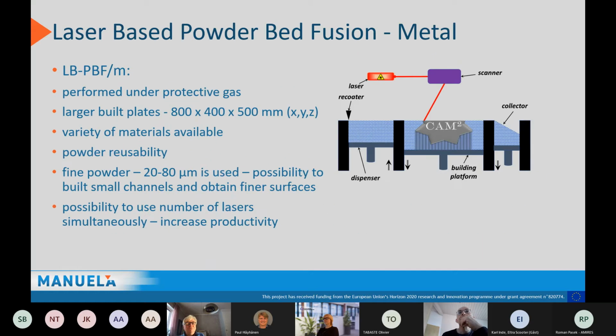Next slide, please. And then we go up to the two technologies. This is a little bit the textbook. If we look at laser-based powder bed fusion, where we use metal, we use a protective gas. We can have quite large build plates, up to 800, 400, 500 millimeter in X, Y, Z. Quite a good range of materials available. We have good capability to reuse the powder, because of course we don't use all the powder in the product we build. So the technology itself must be built so that we have a good capability of reusing the powder.